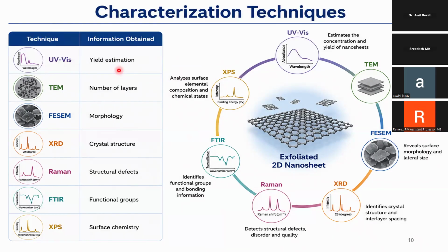Yield estimation is a very relevant thing, and not only that, the band gap of the particles you are getting can be found out with the help of UV visible spectroscopy, because you need to plot the Tauc plot, and from that Tauc plot, that means the indirect band gap plotting, you can find out whether you got the correct particle you are aiming at.